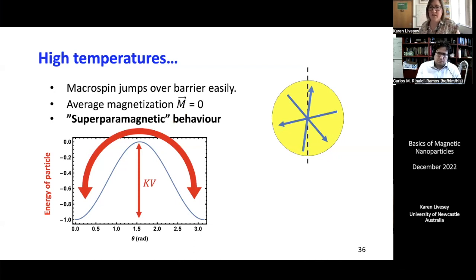If we do a time average, or if we average over a lot of nanoparticles, which is typically what we do, we typically find it hard to measure one particle. If we average over time or lots of particles, we get magnetization being 0. But it's not for the reason we saw earlier. Remember, we saw earlier that when we heat up a magnet large enough, above 820 Kelvin, we lose all order. This time we still have order. We still have the atomic moments lined up. There is still some order here, but for a different reason, we see that the macrospin moment can visit all angles, and so we get no net magnetization in a nanoparticle system.